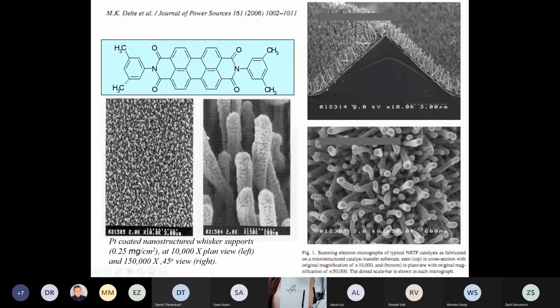Yeah, so then what you do is when you sputter deposit the platinum on there, you can see these tiny little particles. Those are the platinum. So the guys at 3M called the organic whiskers, they called them whiskers. And these little platinum particles on the whiskers, they called them whiskerettes. Okay, so we're whiskers and whiskerettes. I mean, really, this is an amazing material science story. It really is. You know, this guy discovers this amazing, weird thing that happens, this self-assembly of these little whiskers. And then you decide you want to use it for catalyst. You can't support them on a flat surface, so you make this corrugated thing. Like, it's just so elegant and wonderful. It's incredible.